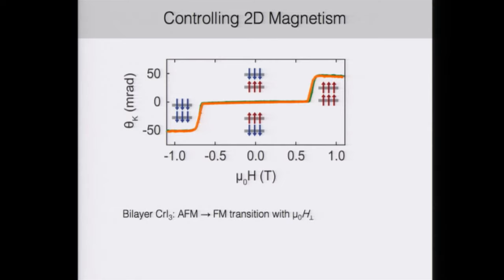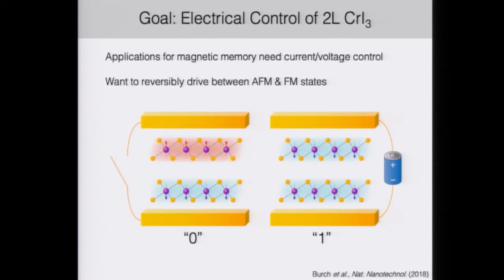As I just showed you, bilayer chromium iodide undergoes this AFM to FM transition with an out-of-plane magnetic field. So we wanted to ask whether there is a way that we can electrically control this metamagnetic transition without just sweeping a magnetic field back and forth. The ultimate goal is to have electrical control of bilayer chromium iodide, which could have applications for magnetic memory, which rely on current or voltage control rather than sweeping a large magnetic field. Ultimately, we'd want to be able to reversibly drive between these AFM and FM states, which you could think of in a memory situation as a 0 or a 1.